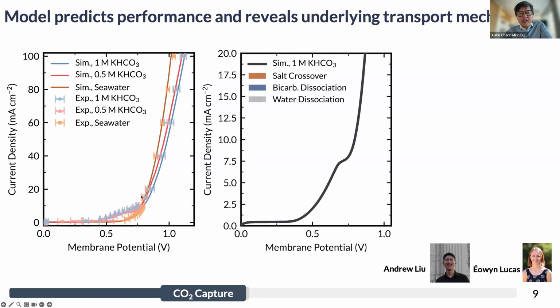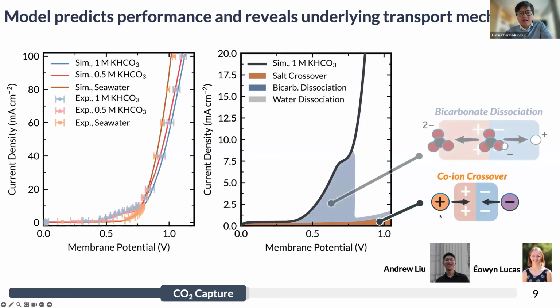And then once we had that understanding, we also wanted to really understand what was happening within this region. And so what's really nice about a model is we can actually break down the current. When you get an experimental result, you don't know necessarily what's happening under the hood, but with a model, we can break down all of the contributions to the current density that are occurring within the system. We see that there's a very small amount of current associated with the crossover of coions to the system, which is good because this coion crossover is typically known as an inefficiency in these bipolar membrane systems.